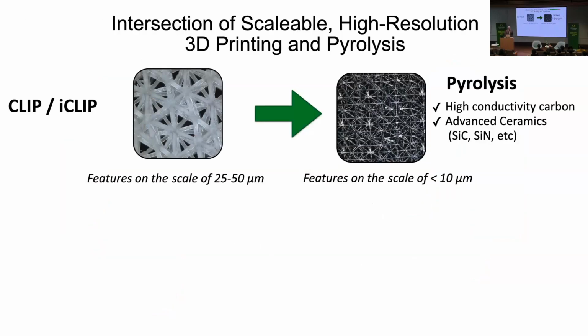And then the last thing I'll leave you with is, I think another big horizon for us is pyrolysis and 3D printing have a really interesting intersection. So carbon fibers, most people are familiar with carbon fiber composites. That carbon fiber is made from a synthetic polymer, typically polyacrylonitrile. You spin a fiber out of polyacrylonitrile. A fiber has a high surface to volume ratio, and you heat it up under a certain environment up to 1200 degrees, and you can remove all the elements and just have pure carbon.